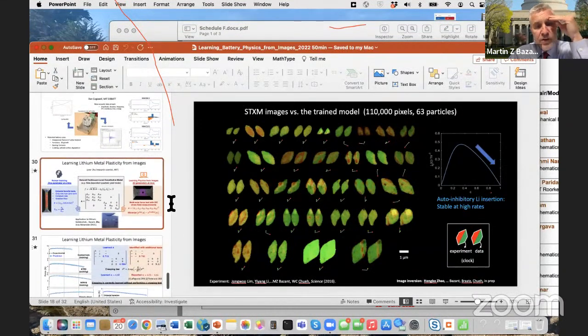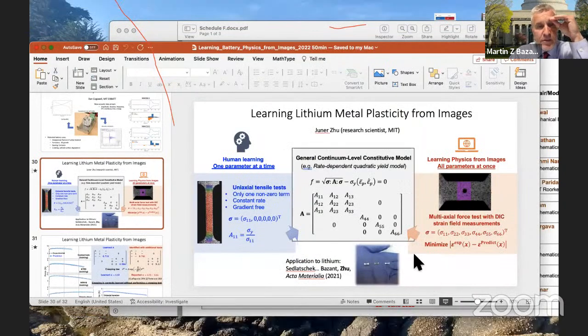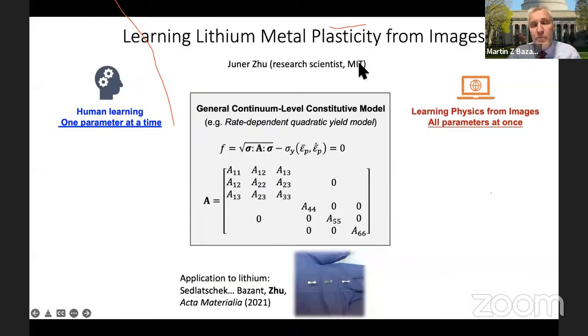So we also learned here, this is a totally different set of problems, but still related to batteries. We learned the plasticity behavior of lithium metal from images. So here we have a rate-dependent quadratic yield model. If you don't know what that means, don't worry about it. It's a certain model of how lithium metal deforms plastically, which means essentially it yields and starts to flow, which happens very easily with lithium. It's actually a very soft material.